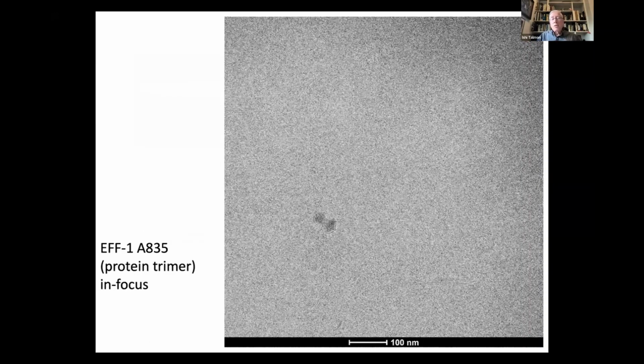Now, one of the most important developments in recent years is what we call the phase plate, the Volta phase plate, which is similar to the phase plate that one sometimes uses in the light microscope. What this does, again with minimum technical explanations, is transform phase differences of different areas in the specimen to amplitude differences. This is a picture taken without the phase plate of a specimen, which is a dispersion of a protein trimer. What you see here is very little. What you see here is a little speck of ice, and then in the background, all you can see is the vitreous ice.